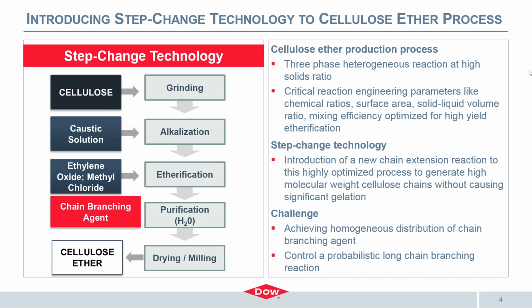This is a pressurized, high temperature cellulose ether production process. It's a three-phase heterogeneous high solids reaction, and unfortunately, or probably luckily, all chemical and engineering parameters have been optimized for high yield etherification. But in the end, no one really anticipated the addition of a chain branching reagent at the time. So the engineering challenge was to introduce a branching agent to an already optimized process, while at the same time preventing gelation during etherification through homogeneous distribution of our branching agent, because finally we needed our cellulose ethers, also the branched ones, to remain fully water soluble.